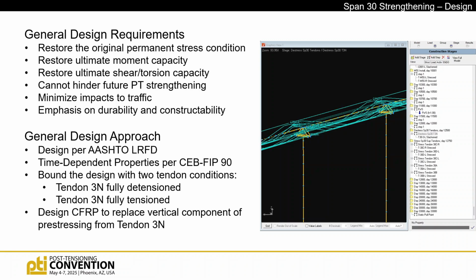We had a big benefit here in that we had 2 extra tendons in this span than what we had in the other approach spans. So we were a lot further from the principal tension limit and not as much concerned about getting that drape portion of the tendon restored. So we were able to, we'll see in a minute, go with a much simpler solution than what we showed previously for span 16. We also bounded our design on the assumption that that tendon was completely lost and completely intact. So we wanted to be able to replace its full effect without overstressing the structure.